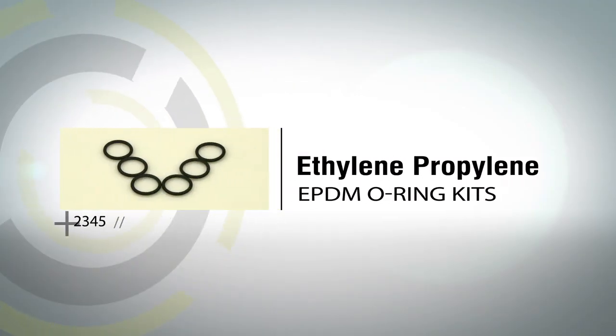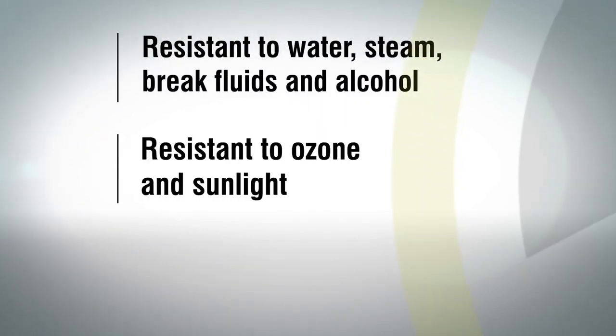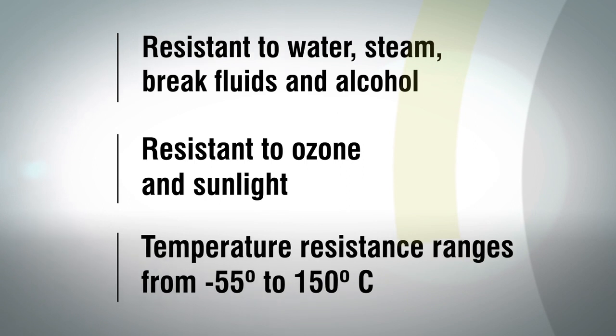O-rings made out of ethylene propylene or EPDM have excellent resistance to water, steam, brake fluids, and alcohol as well as ozone and sunlight and have temperature resistance from minus 55 degrees Celsius to 150 degrees.